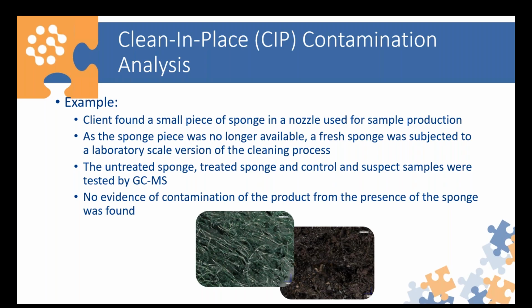And what we did is we took the untreated sponge, the treated sponge, and then control and potentially suspect samples, and we analyzed them by GC-MS to look for the presence of any volatile compounds that might be contaminating the sample. Unfortunately, in this case, we didn't see any evidence of contamination of the product from the presence of the sponge, and we're able to give them some peace of mind.